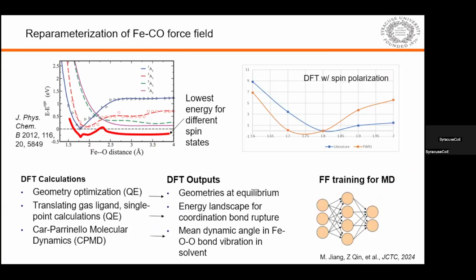As I said, there's no good force field, so we built our own. We use a DFT calculation, which is an ab initio statics calculation, and also CPMD, which is an ab initio dynamics calculation. Using both results, we can characterize the bond length and the bond energy, and use that as the input to train a force field and make it suitable for classical MD simulation. The reason we want to do MD is that once we simulate the binding from carbon monoxide to hemoglobin, we also need to consider the water environment. But if we consider water, DFT will be very difficult to do, with too many atoms.